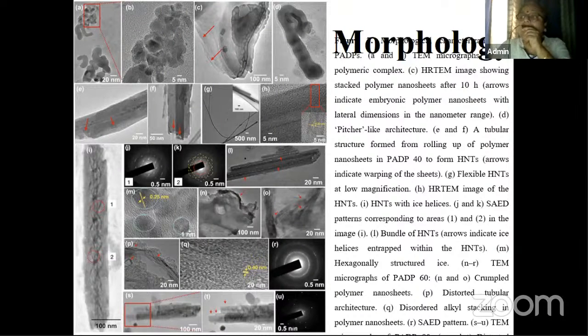So it will pressurize in the area of nano confinement, because that is automatically done. In our case, we are experimentally proving that, but in some cases they have applied pressure from outside to achieve this nano confinement. So nano confinement is one of the important parameters to get the exotic nanostructures. Further, shape selectivity, and how the processed molecules, reactants, transition states, and products fit in the confined area at the nanoscale, plays a crucial role for the occurrence of successful transformation. And in that respect, deriving nanomaterials with various shapes can lead to controlled enhancement of particular chemical reactions at their interior.